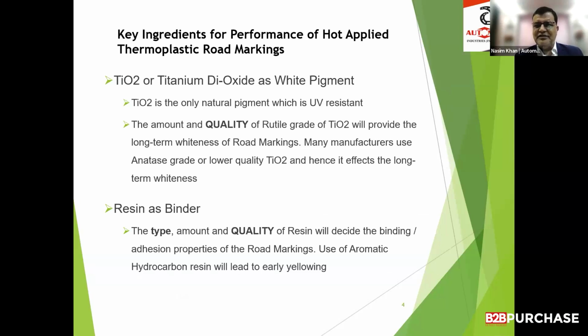So, coming to the key ingredients for the performance of thermoplastic road marking: titanium dioxide is a major one, used as a pigment for whiteness. It is the only natural pigment which has UV resistance and sustainable whiteness for the long term. But there are grades like the rutile grade and the anatase grade. The anatase grade of titanium dioxide is a little yellowish, and hence does not give you long-term whiteness.